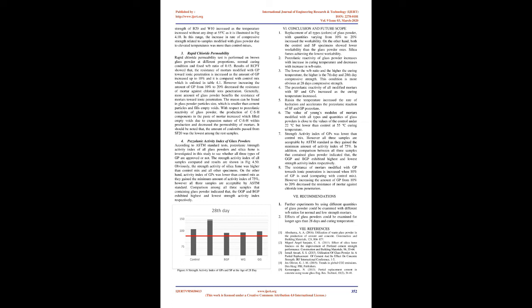The following charts illustrate the compressive strength of mortars prepared at different W/B ratios and different temperatures. The compressive strength of samples prepared in each condition is compared together and with control mix to evaluate the effect of glass powder in different situations. As it has been shown in Fig 1, at standard temperature and W/B of 0.35, mortars that were modified with different types of glass powder expressed lower compressive strength at the early age, compared to control mix.